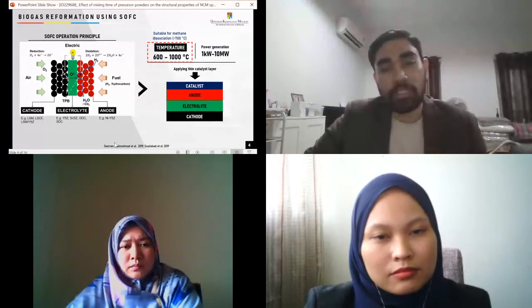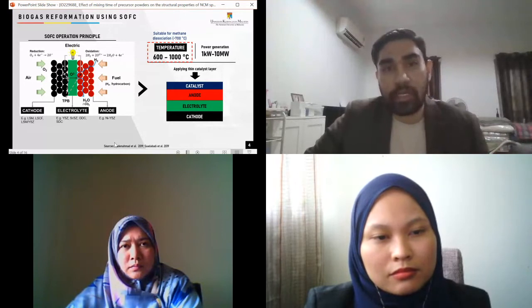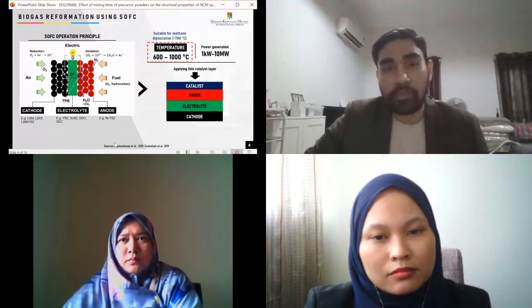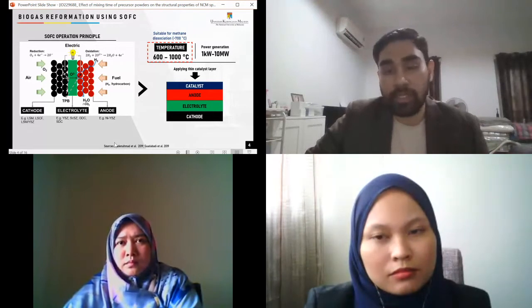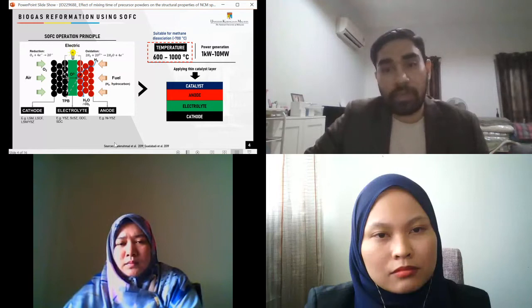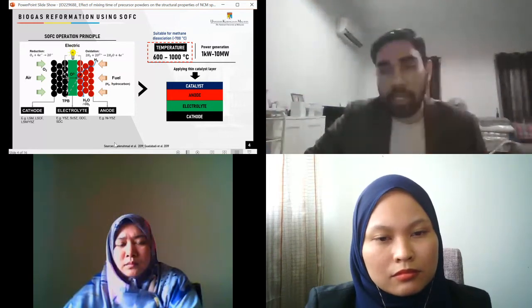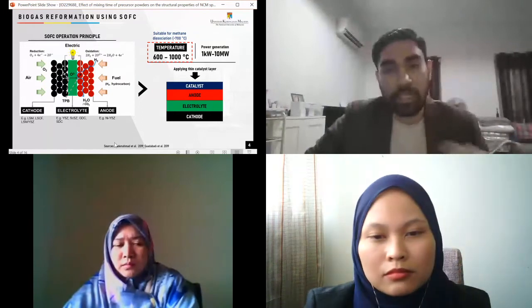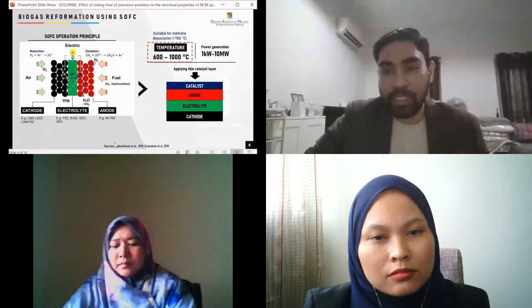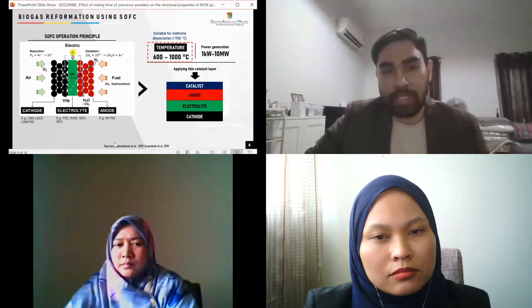Furthermore, the temperature of the device is around 600 to 1000 degrees Celsius. So this temperature is suitable for methane dissociation, which usually occurs at 700 degrees Celsius. And to increase the reforming reaction inside the device, usually researchers apply an additional layer which contains catalyst to increase the methane reforming inside the device.